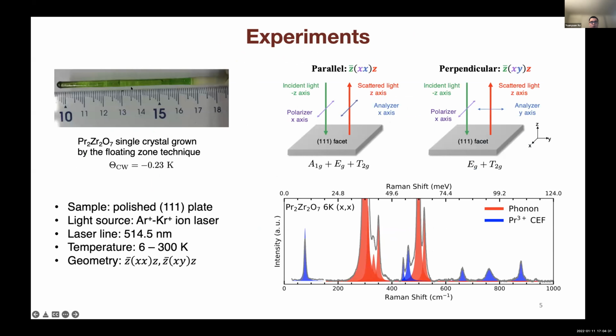This is the sample we used in this experiment, and we cut a thin plate with 111 orientation from the single crystal rod grown by the floating zone technique. We performed measurements in the temperature range from room temperature down to 6 Kelvin. And we used two geometries to identify the symmetry. In xx polarization, the polarization of the scattered light is parallel to the polarization of the incident light, while in xy, the polarization of the scattered light is perpendicular to the incident light.